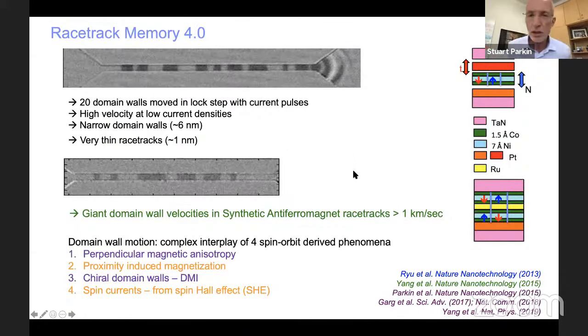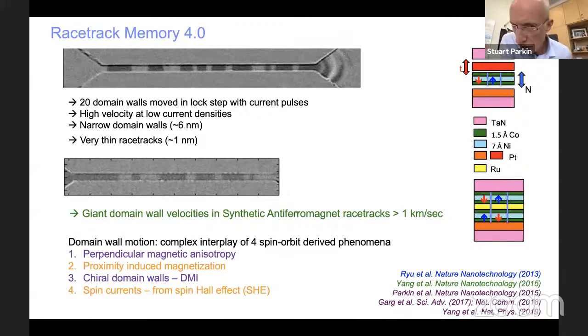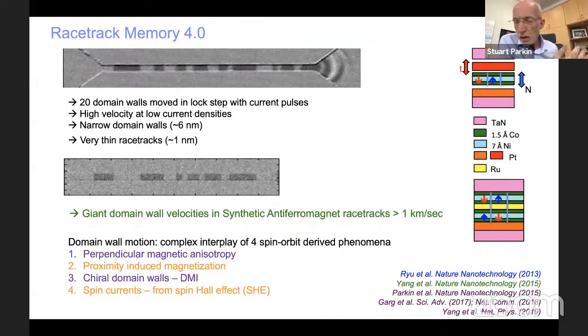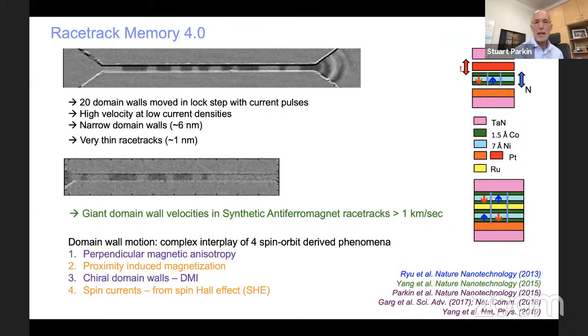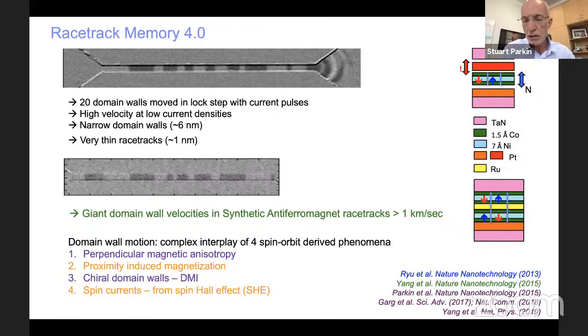So again, without going into many details, to date most of our work looking at the current-induced motion of domain walls is in racetrack devices or nanowires. Horizontal nanowires are shown here, of the order of 2 microns wide. So we could use magneto-optic Kerr effects, or optical effects, to detect the domain walls. The upper shows you a series of domain walls moving at 300 meters per second, and the lower one now shows a synthetic antiferromagnetic racetrack where the domain walls are moving at more than a kilometer per second.